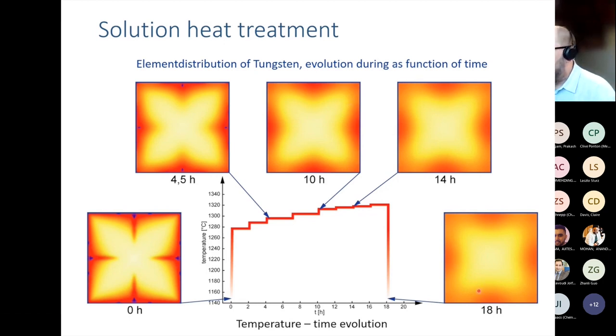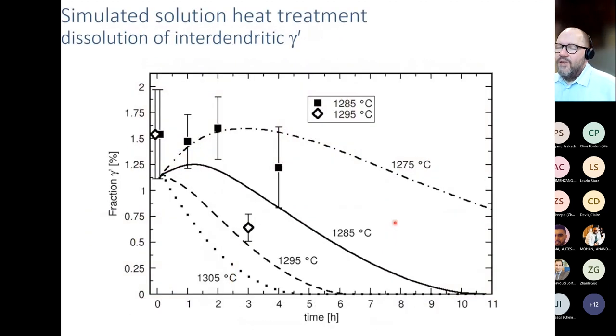But we find that even after 18 hours, time and temperature weren't enough to completely eradicate the tungsten segregation profile. So there's still going to be slight compositional variation even after 18 hours of heat treatment, going up to 1320 degrees C, which is quite warm. And if we then evaluate the amount of gamma prime present in the microstructure over time, we end up